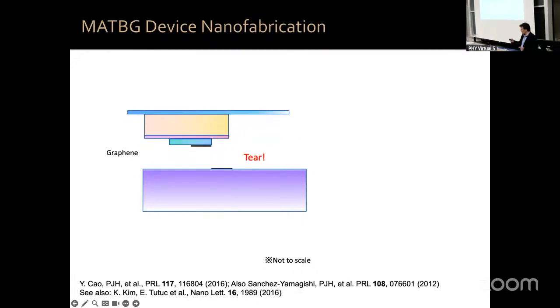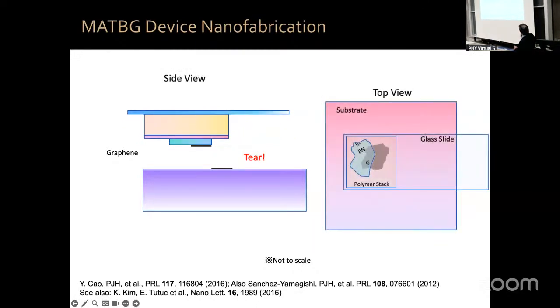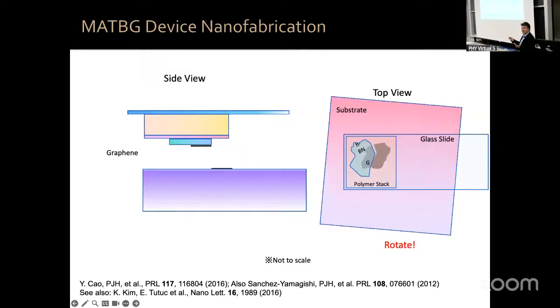And then we come and we tear half of the graphene. Now, from the top view, what we have is the substrate with half of the graphene, and then the glass slide with the polymer stack with the hexagonal boron nitride and the other half of the graphene. These two graphene sheets are at different height, but the position and orientation of their atoms, carbon atoms in both sheets, is correlated because they came from the same crystal.